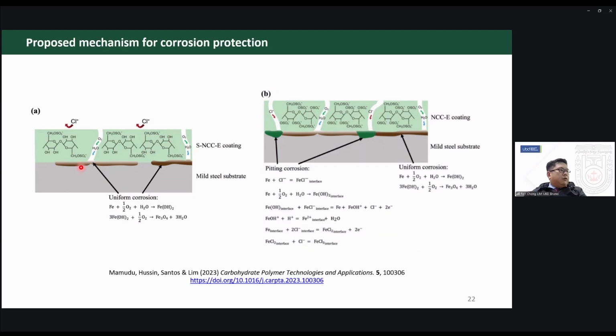So we saw that for our sulfated nanocellulose, we do have actually still corrosion happening. From the time constants, we did confirm that there was, at least for these ones, still corrosion happening, but we say that it's actually just the uniform corrosion that occurs on the metal surface with the hydroxide ions. Now this is actually okay, because as long as the coating is intact, the rust that forms cannot come off. You can still deem the system as working.